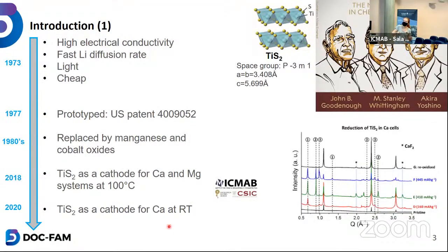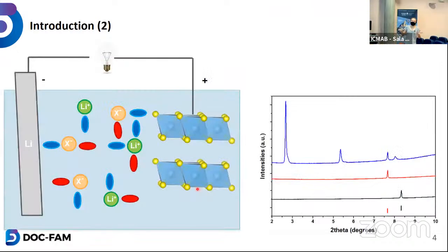Yes, calcium and magnesium. In 2018, when I started my PhD, ICMAB had just published a paper where they managed to do reversible electrochemical intercalation of calcium in titanium disulfide. At that time, the state of the art was 100 degrees. However, the topic is evolving quite fast, and as you can see, last year they managed to do the same thing, but at room temperature. There is one little problem, however: calcium does not enter alone in the titanium disulfide. You also have solvent co-intercalation, and the solvent in question is propylene carbonate. So I'm going to explain quite fast.